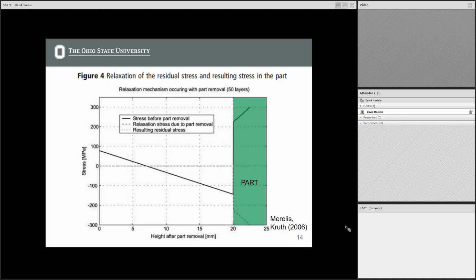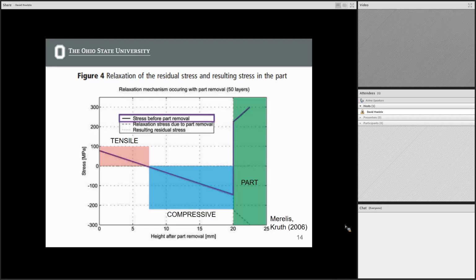whereas everything else is the base plate. There's actually an error, I believe, in the paper with this figure. It says height after part removal on the x-axis, but I'm fairly certain that is incorrect. It should be height before part removal. So we have our tensile stress zone that we just showed with that figure before. Here, our compressive stress zone, and this is the stress going from the bottom of the base plate all the way up through the top of the part.